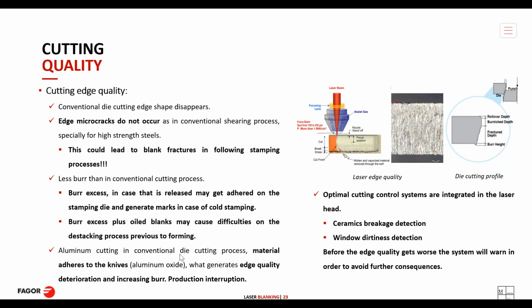And finally, talking about aluminum, the material in this case adheres more easily to the knives. It's not the aluminum, but the aluminum oxide, and this generates that with time the edge quality goes deteriorating, and it will lead to a burr increasing. And with time, this will lead to a maintenance operation of knife cleaning that provokes a production interruption.